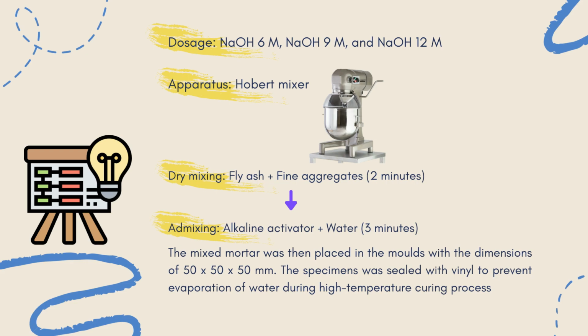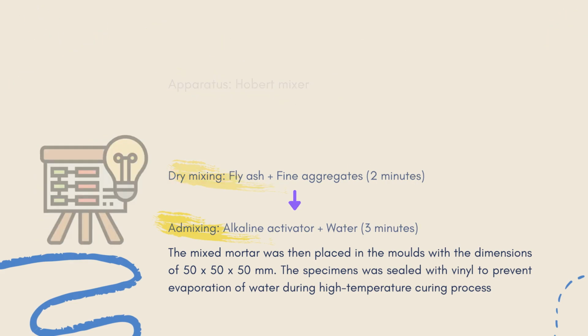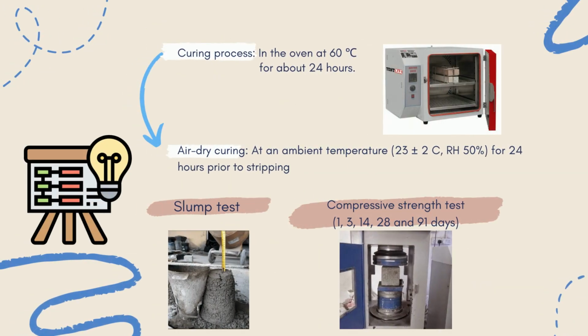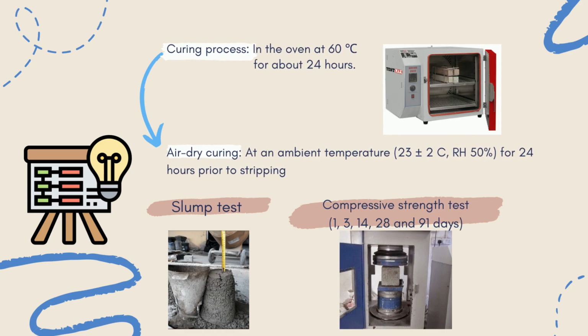From the figure, the higher the molar concentration of sodium hydroxide, the higher the compressive strength if fly ash is used as a binder, and strengths greater than 45 and 46 megapascal developed at 56 days for molar concentrations of 9 and 12 M, due to the activation of the reaction of the internal alumina and silica caused by the increased breakage of the glassy chain of fly ash.